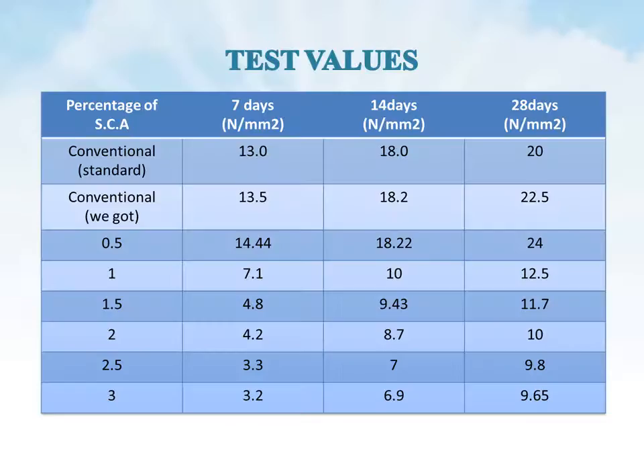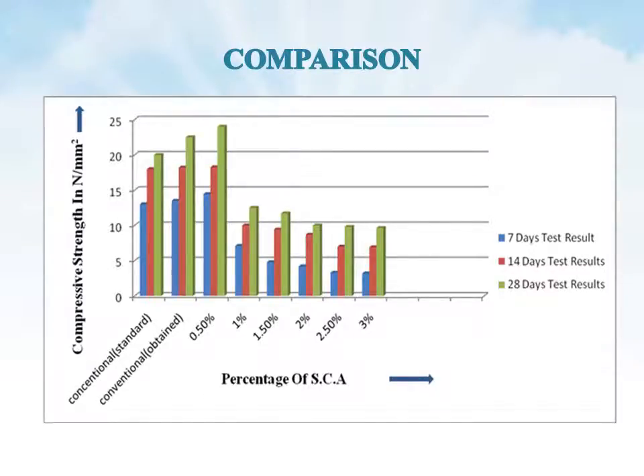Compressive strength. We conducted compressive strength tests for 7 days, 14 days and 28 days for conventional and self-curing concrete. We got these values from the test we conducted. From these values we got the optimum value at 0.5% of sodium lignosulphonate, which is self-curing concrete: 7 days 14.44 Newton per mm square, at 14 days 18.22 Newton per mm square, at 28 days 24 Newton per mm square, which is greater than conventional concrete. This is a comparison chart of the self-curing and conventional concrete.